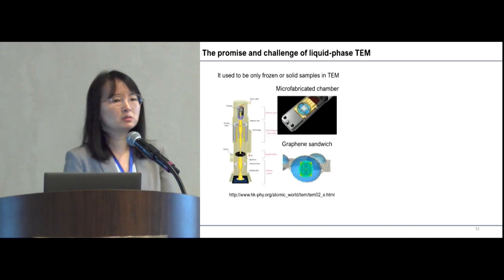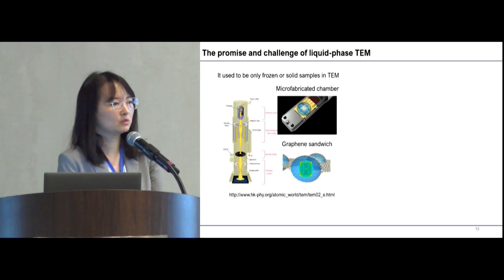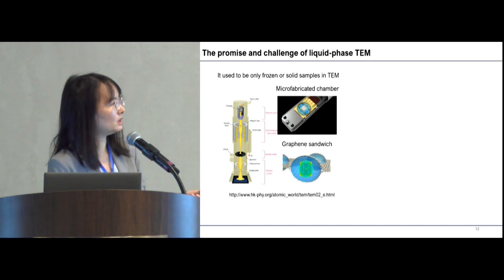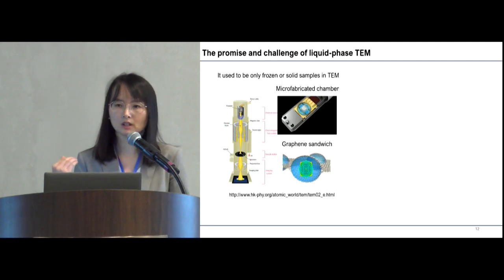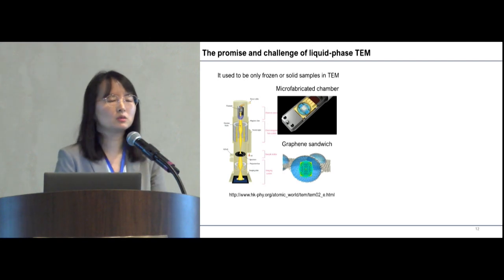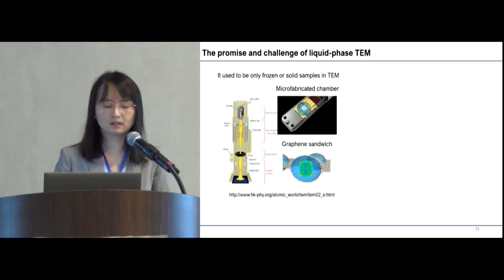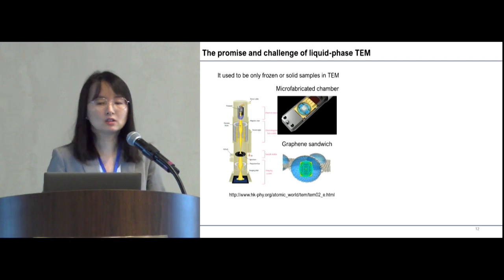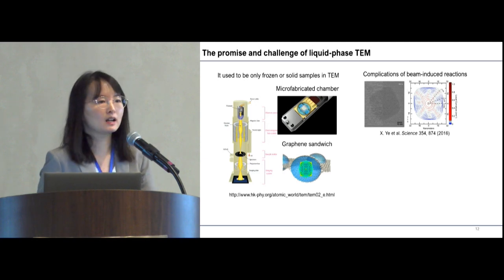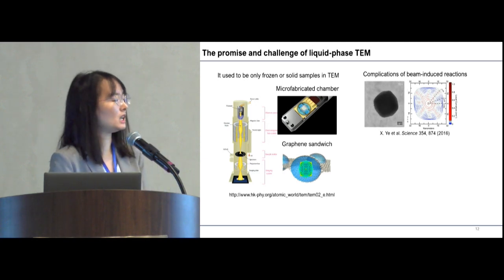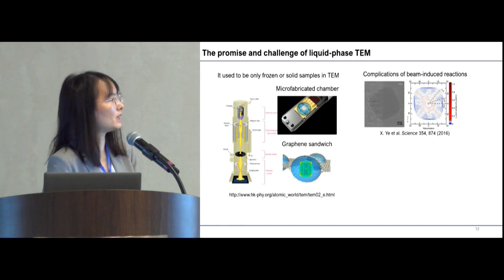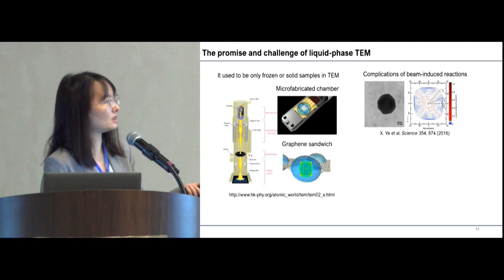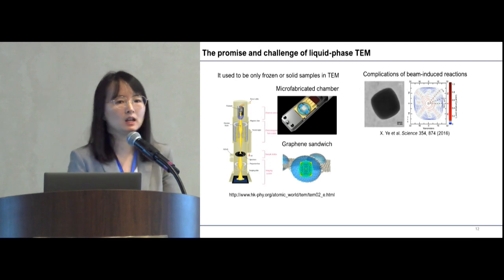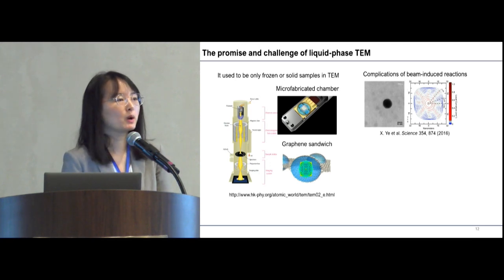So here comes my group's unique contribution. We introduced liquid phase TEM to observe the self-assembly pathways of nanoparticles. In particular, we use this type of microfabricated chamber, which allows you to do in situ TEM imaging together with modulation of the liquid environment. But before we go too far, let's keep in mind, the electron beam has a high energy, so you can easily initiate beam-induced nanoparticle reaction as shown here. You can see the nanoparticles getting etched away in the liquid. And that's what we want to avoid.